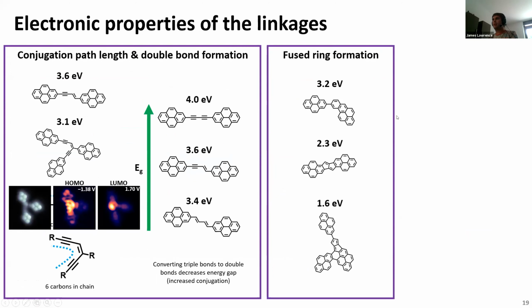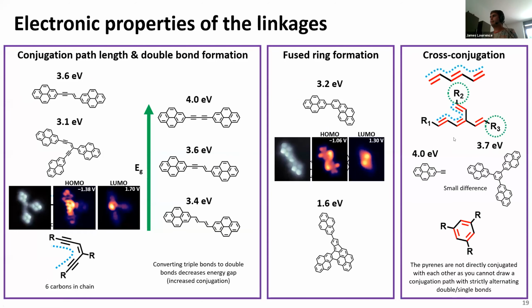Okay, so I've probably already explained this, but the formation of the fused rings here clearly reduces the energy gap significantly with the addition of these to the pyrene moieties. And then, of course, we have the effect of cross-conjugation here, where we can't strictly form alternating single, double bond chains between different moieties. So, for example, in these two parts here, between R2 and R3, we have to draw two single bonds in a row, which reduces the amount of conjugation between them. And this symmetric trimer here is a very nice example of this, because if we consider this as an R group in this diagram, to go from this pyrene to this pyrene, we always have to go through two single bonds, which reduces the conjugation between them. It acts maybe more like just having a pyrene with a benzene ring on the end.